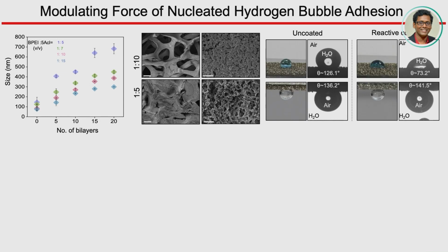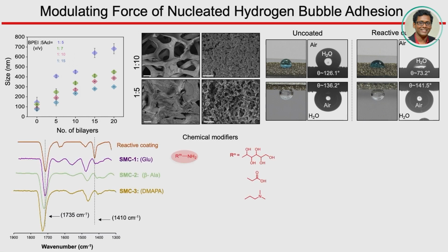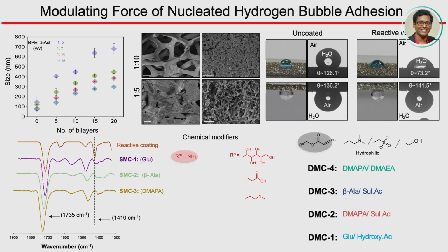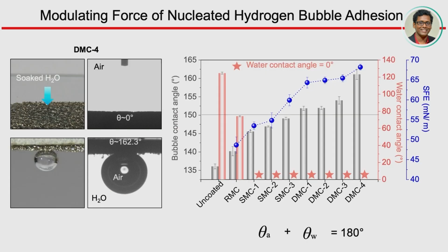And after deposition of this reactive coating, you will see the bubble repellency improves a little bit compared to the uncoated one. But when you go for single modifications with these modifiers, or this type of modifiers, which is called dual modification, the DMC is abbreviated as dual modified coating, and these are single modified coatings. We found this is the kind of modification where you have the tertiary amine on both sides, and you see this bubble repellency is maximum, 162, and what we also observed is that irrespective of single and dual modification, they all give super hydrophilicity. But that doesn't mean that all these interfaces will give super aerophobicity.